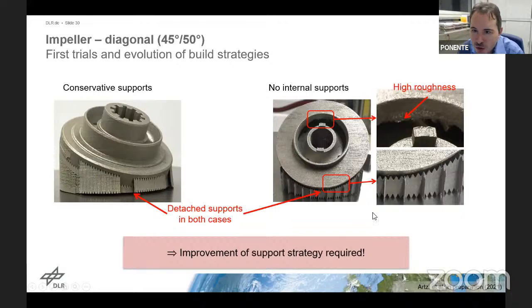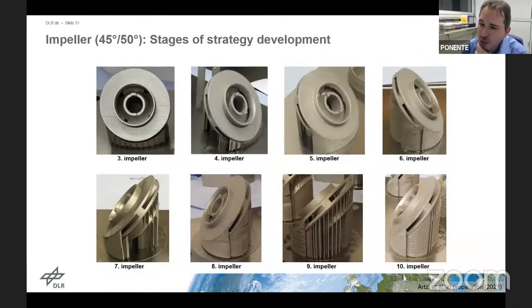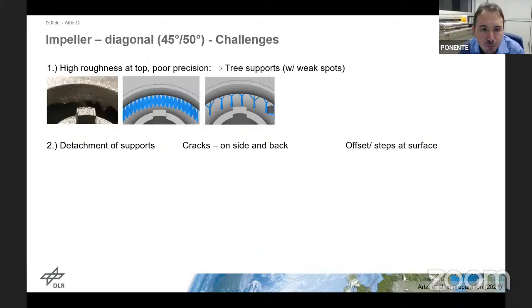And in order to address all these issues, we went to an, let's say, empirical, iterative development of build strategies with customization of supports and analysis of the part in between, which then led to the build strategy shown on the right-hand side, the 10th impeller, which has a rather complicated support strategy. Some aspects that we addressed here were this high surface roughness in this top surface.